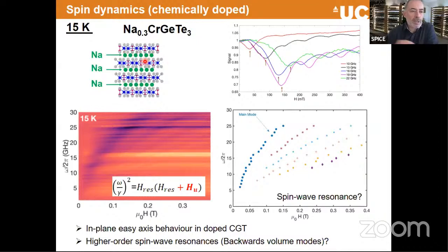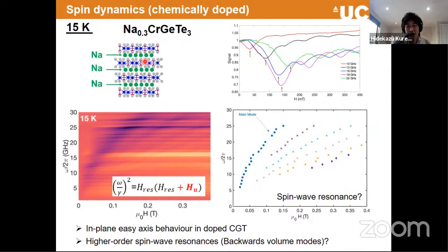So I'll ask the question for Banan Kerry, who cannot use his microphone at the moment. How do you intercalate CGT with the sodium atoms, during growth or after exfoliation? Okay, so this is the chemistry part. That's done by my colleague at UCL who has a strong background in chemistry. What I can tell you is that there is a solution, and you just dip the pristine CGT in it, and then there is a chemical interaction or reaction. Basically, sodium is soaked into the van der Waals gap. So this is a purely chemical process. Then we take out of the solution, pick up the sample and measure.